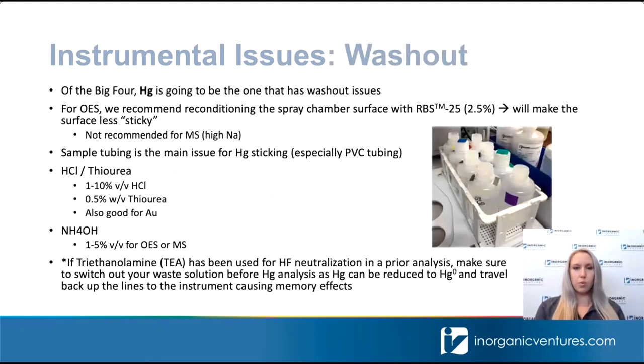That brings us to washout. Of the big four, mercury is definitely going to be the one causing issues for washout. Again, mercury does have a tendency to stick to plastic components if it is in a nitric acid matrix. And your main source of the sticking is going to be your sample tubing. That PVC tubing has some real issues with mercury sticking. So one thing we recommend, if you are seeing a lot of mercury washout, is just going ahead and replacing all of that tubing, and that should really help with those issues.